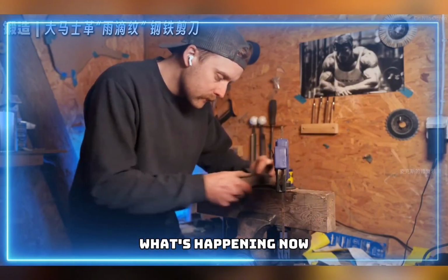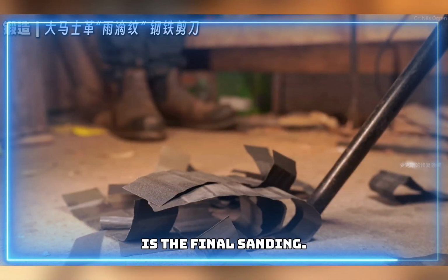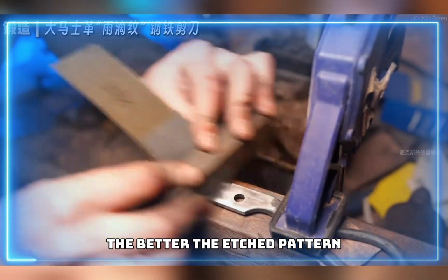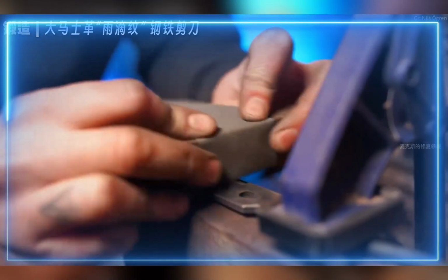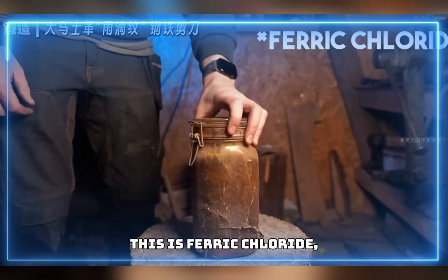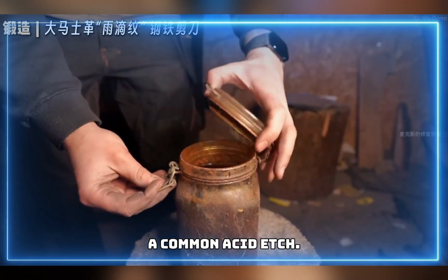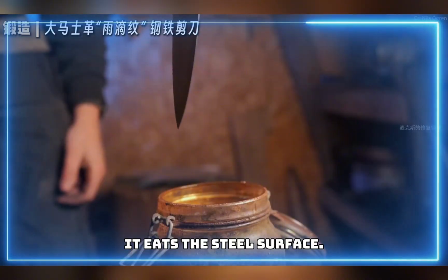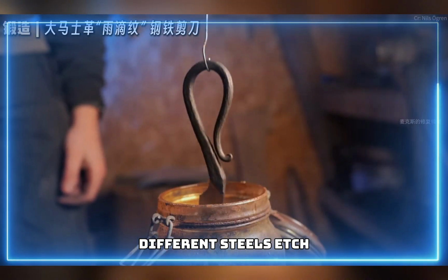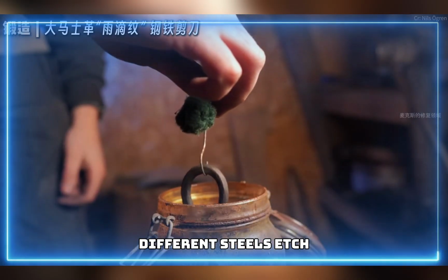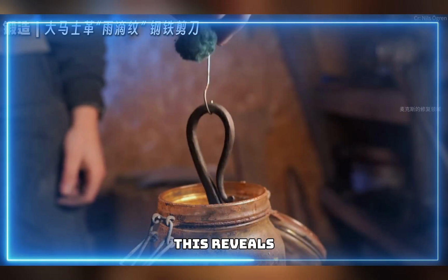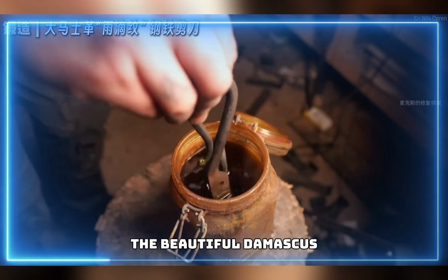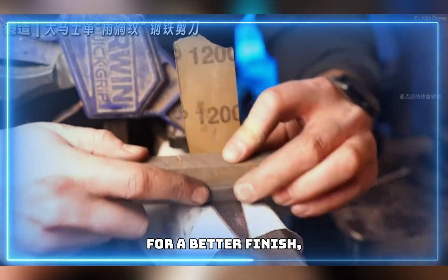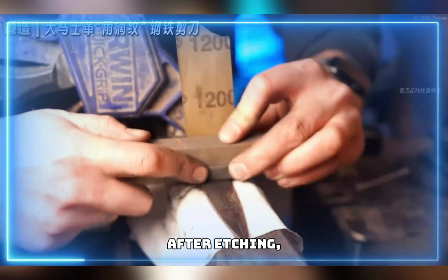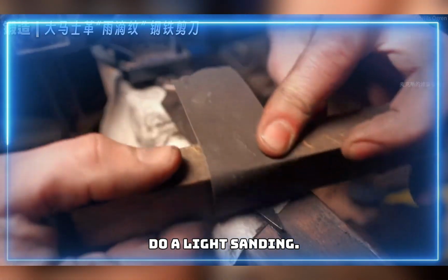What's happening now? Is the final sanding? The smoother it is, the better the etched pattern will look. This is ferric chloride, a common acid etch. It eats the steel surface. Different steels etch at different speeds. This reveals the beautiful Damascus pattern for a better finish. After etching, do a light sanding.